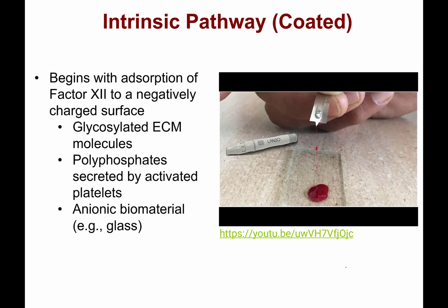Now, the intrinsic pathway is a little bit different. This begins actually with adsorption of factor 12 onto a negatively charged surface. So that right there, you should say, oh, if I have a negatively charged biomaterial, that's going to be really bad for a blood contacting device, because factor 12 will adsorb and you get coagulation via the intrinsic pathway.